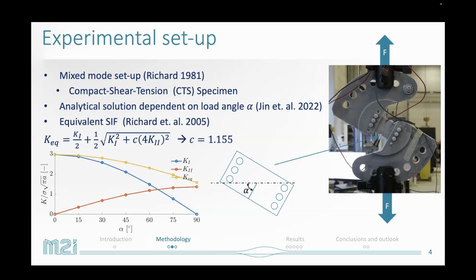And finally, we have an equivalent stress intensity factor, which we use to evaluate our fracture results. And this equivalence is based on literature, also developed by Richard. And you see there is a material constant C, which is often taken as 1.155 for steels, which corresponds then to a more or less von Mises equivalent stress principle.